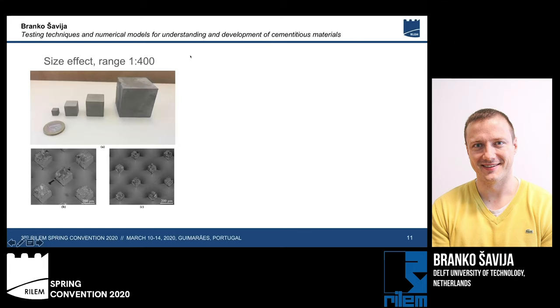And we subject them to the same boundary conditions. Because these specimens are glued at the bottom, we also do the same with all the specimens. So we glue them at the bottom and subject them to splitting at the top. And in this way, we can, in a way, estimate the splitting tensile strength of our material.